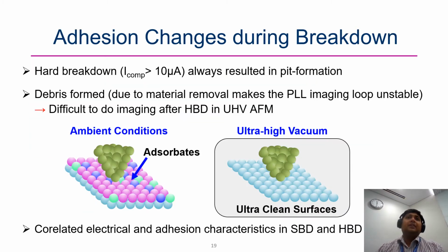In our experiment, we also found that the hard breakdown in ultra high vacuum conditions for the CVD hBN always results in a very large pit, as earlier groups have observed. But since we are working in ultra high vacuum and were using frequency modulation imaging mode, the debris formed was huge, and it was making the phase lock loop imaging very unstable. So we were unable to image the hard breakdown spot.